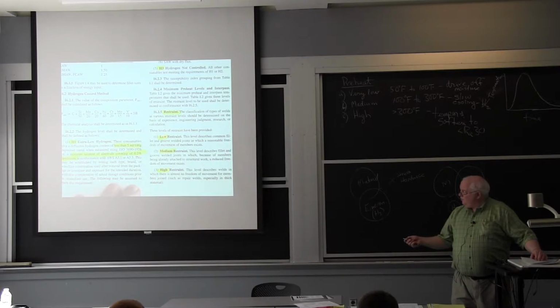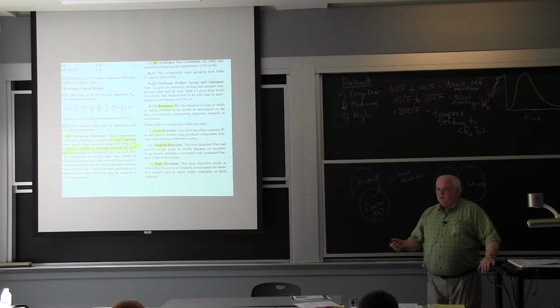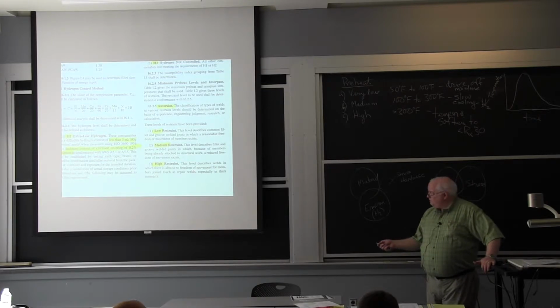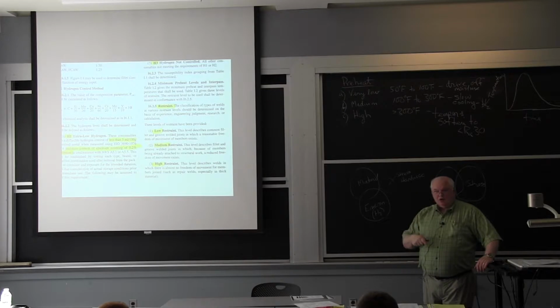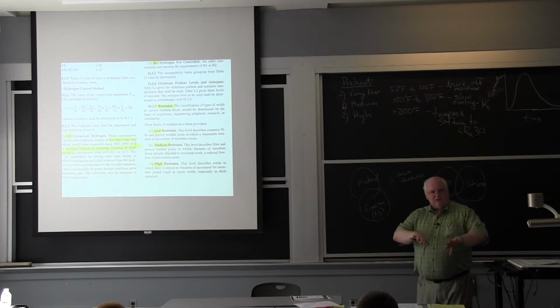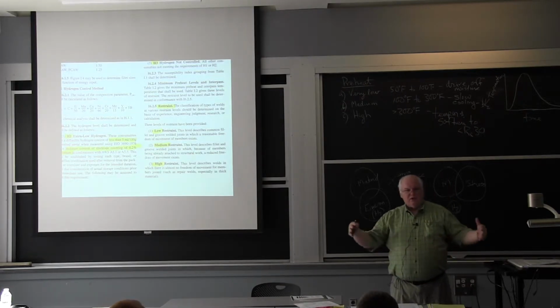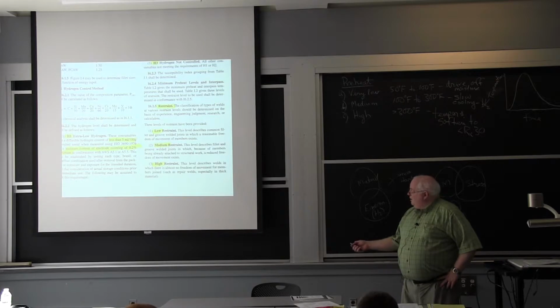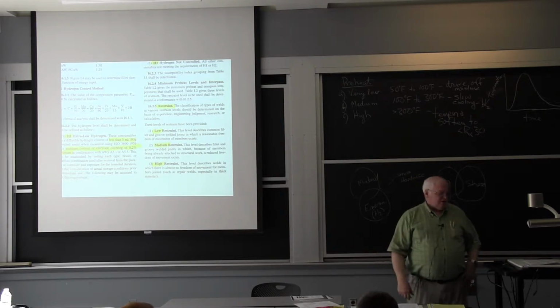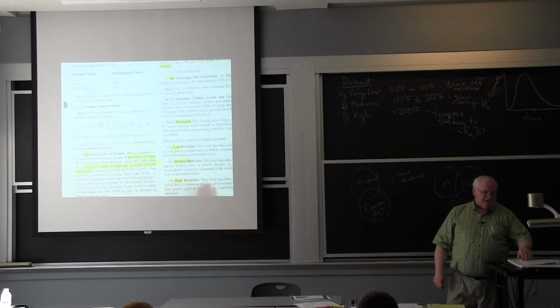You have to determine whether you have low, medium, or high restraint. And this is not quantified. We don't know how much stress you've got, but this basically says it's thicker steels or repair welds where the members can't move, okay? Like a circular patch, oh, that's very high restraint, okay? But a medium restraint might be a heavy plate, but it's allowed to take the V shape. It's not welded to other things on either side. Low restraint, it's either thin material or it's not already welded to other things.